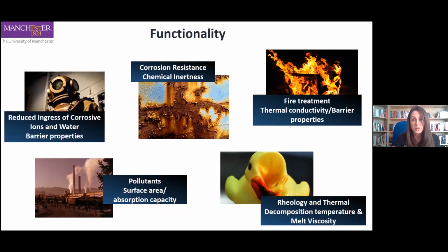Also, graphene's got a huge surface area, and we can control the surface area and tune the surface chemistry. So if you think about it, different pollutants have affinity for different surface chemistries and morphology. Graphene has all these absorption sites, which means it's being studied for the absorption of pollutants within coatings: heavy metals, gas, waterborne pollutants, all kinds of things.